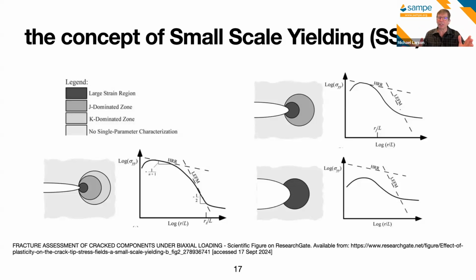the singular stress field. So since that is the case, we can imagine cutting out a zone around this crack tip and putting boundary conditions on that cut surface that replicate the known stress distribution from the singular solution scaled by K. Hence, we have a sample that we can test according to an ASTM standard for getting stress intensity factors, a test that we can assign a critical value, the fracture toughness, to a material, and then use that as long as the cracks aren't causing nonlinear zones to intrude on some boundary that is well defined by our